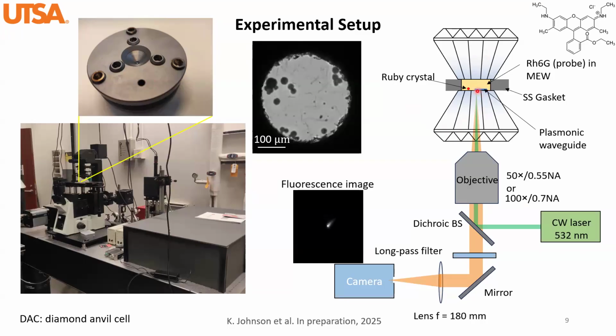Just inside the cell, we loaded the plasmonic waveguides, which are wires here, as you can see in this image. We also use a pressurizing medium, a mixture of methanol, ethanol, and water in the ratio of 16:3:1. This allows us to create hydrostatic pressure up to 10 gigapascals. Inside the solvents, we dissolved dye molecules, rhodamine 6G, as a probe to tell us where the surface plasmons are.